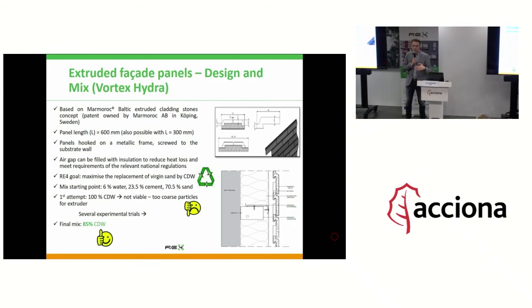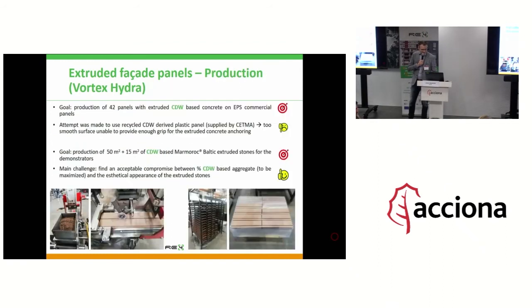in different trials, Vortex tried to optimize the replacement level. 100% didn't quite work with the CDW mineral fraction available due to some problem with the extrusion, but at 85% they achieved good results. In the project, in a preliminary upscaling, creating panels for testing, Vortex succeeded in making 42 panels using CDW mix, and also produced several panels for the final demo buildings.